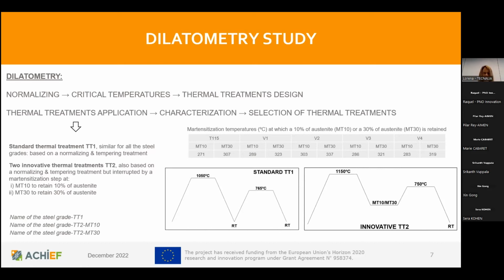But in order to do so, first of all, we need to calculate the martensitization temperatures, MT10 and MT30, for each steel grade, because these temperatures depend on the steel grade composition. So once we get to know these temperatures for each steel grade, we have enough knowledge to apply successfully these 3 thermal treatments.